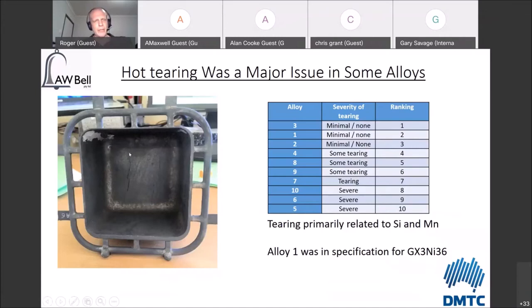There's a hot tear over on the left-hand side here, and there's more hot tearing through on the right-hand side. Now this is the thickest wall, and generally when hot tears did appear, they appeared on the thickest wall. Of course, there's gates behind them on the 4 corners, so it's no real coincidence that we saw this issue. But generally, when we did see tearing, it was not on the thin walls. It was generally on the thicker sections.